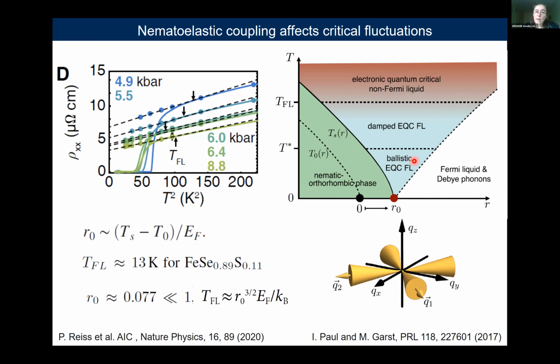So this nematoelastic coupling, this is a phase diagram of what could happen in the presence of the nematoelastic coupling, that we can also expect that the system will have non-Fermi liquid behavior at high temperature before it becomes a Fermi liquid. And this is what we detect with pressure, this transition to Fermi liquid behavior at low temperature, which allows us to estimate what that coupling could mean and how that coupling could also lead to the shifting of the phase diagram and the position of its critical point. But because in quantum oscillation we measure orbitally averaged mass, and if the criticality is only allowed along certain directions because of this coupling, then an average effect will not show any divergent correlation at the nematic endpoint.